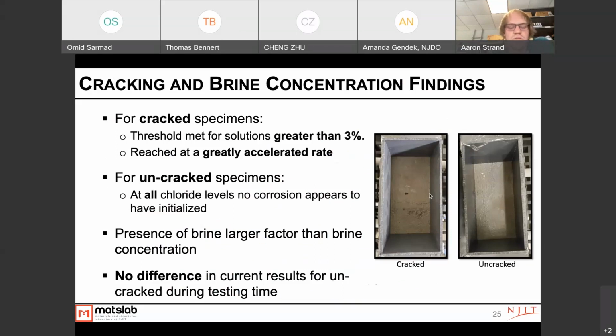And the presence of brine was a larger factor than just the brine concentration, as a 3 times increase in the concentration of the brine didn't result in a 3 times increase in the corrosion values that you were seeing. And there's no difference in the current results for the uncracked specimens during our testing time period.